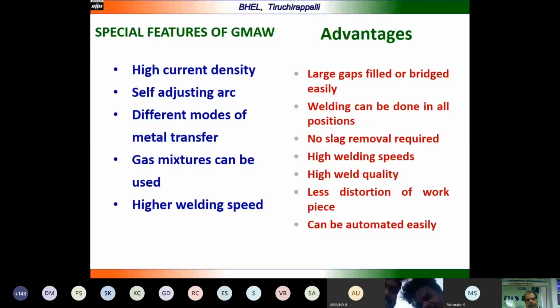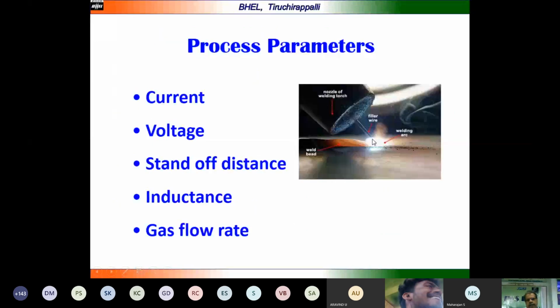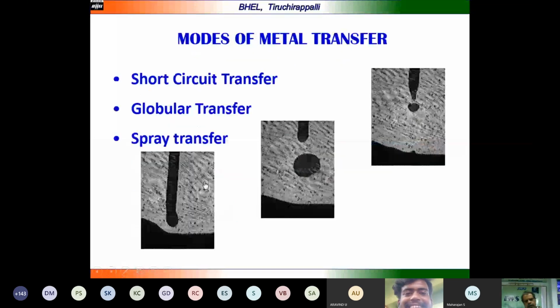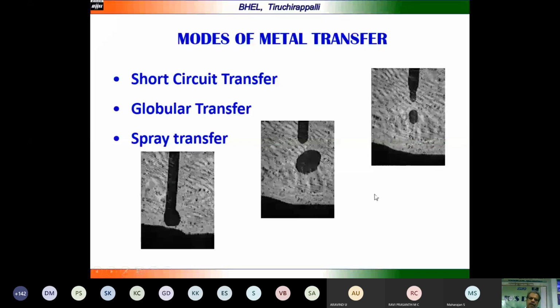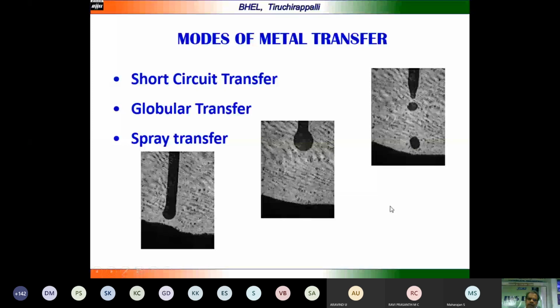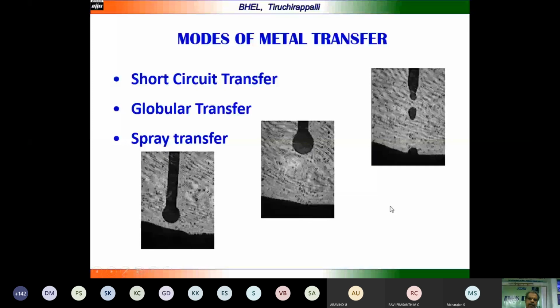The important process parameters are the current, the voltage, the standoff distance, which is the distance between the tip of the electrode and the job, the inductance level, and the gas flow rate. These are very important parameters when you are working with this process. As I told earlier, there are 3 modes of metal transfer. One is the short circuit transfer, which is used for low current and thin jobs, globular transfer is intermediate, and the spray transfer mode is the continuous mode. You can see the difference in how the metal is getting deposited in all the 3 modes actually.